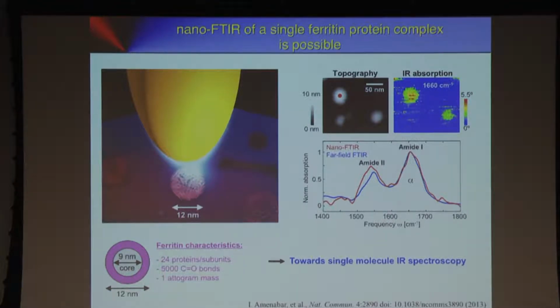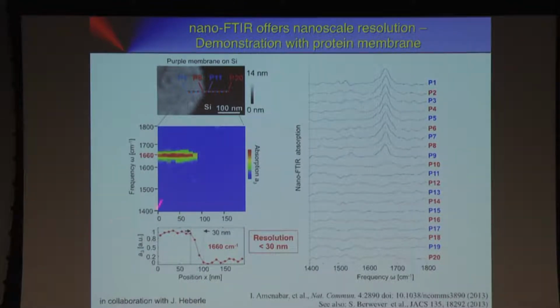So it's a really sensitive technique already, and we are confident that we can push this to a single molecular level, but a couple of things like photon flux and the sharpness of the tip need to be improved. Regarding resolution, we scanned a purple membrane. That's a protein membrane about 7 nanometers thick. We took spectra at each pixel along this line profile and traced the amide 1 band, going in 10 nanometer steps. This is the spectral axis, the frequency, so a spectral-spatial plot. We scan along here and see this peak nicely. It persists until we reach the edge of the protein membrane, and then it vanishes pretty quickly, within 1 step more or less. If we trace the intensity of the peak, we get this line profile, and within 30 nanometers we go from 100% signal to about 0% signal. So we have a resolution of at least 30 nanometers, depending on the criteria. We could eventually even claim 10 nanometer resolution.